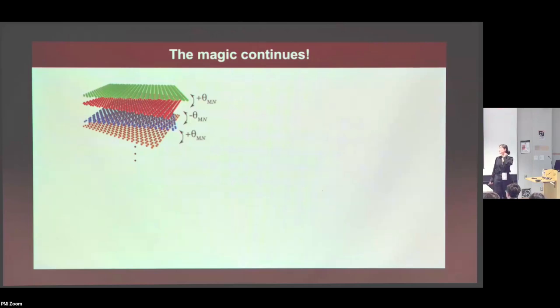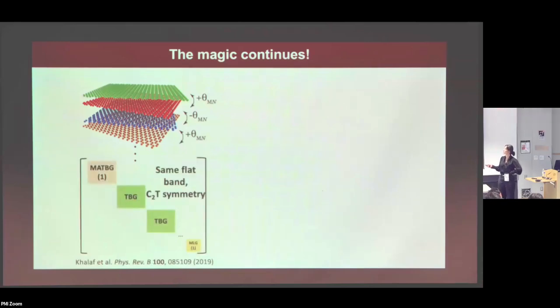Okay, so we looked at twisted trilayer graphene, but I want to mention that that's not the end of it, because as long as your structure is this same structure where you have this alternating plus theta, minus theta, plus theta, minus theta, up until whatever number of layers you can experimentally realize, you would still be able to form some sort of magic angle with exactly the same principles, where you can block diagonalize this very big Hamiltonian for the number of layers, and you can always try to make one of the blocks into a flat band like block, so that you have the flat band, and then the other bands will just be existing there.